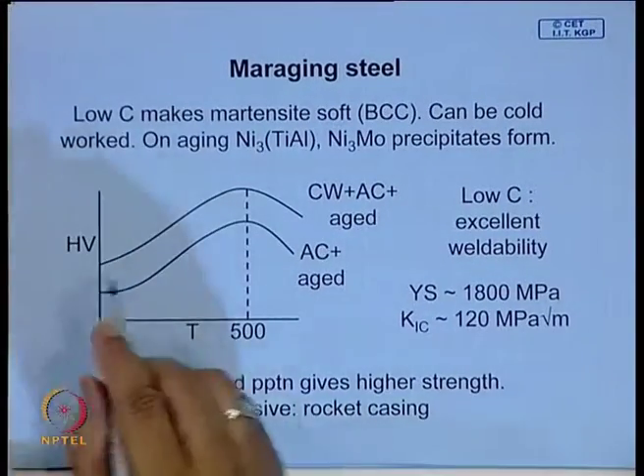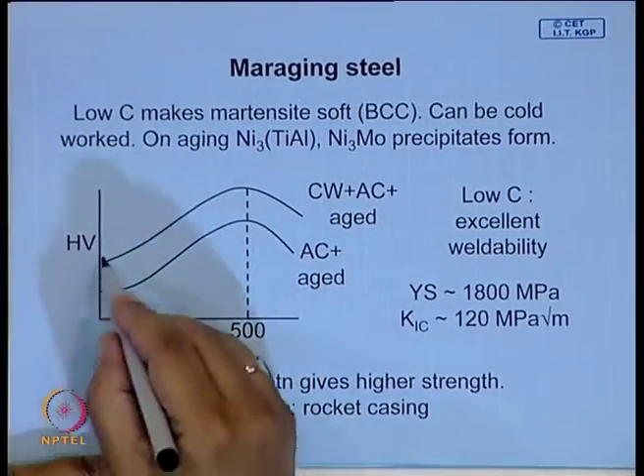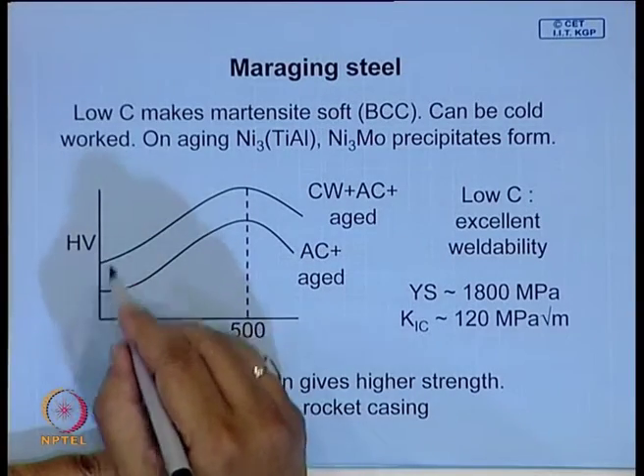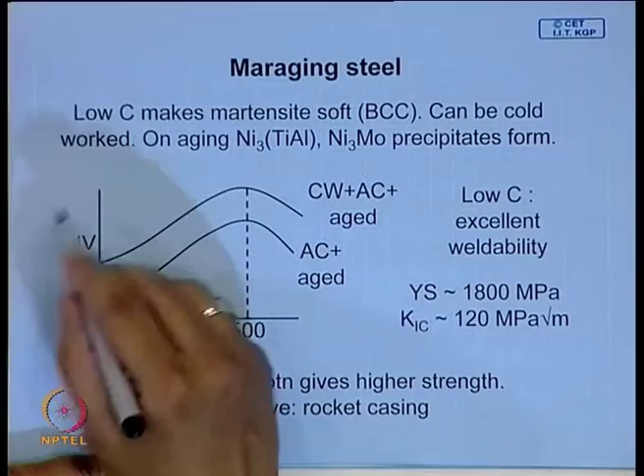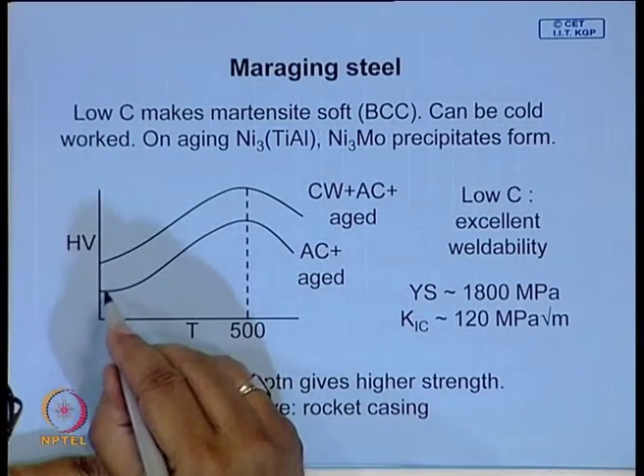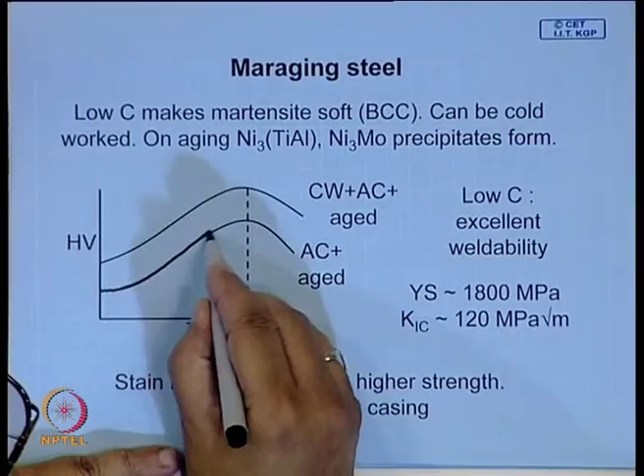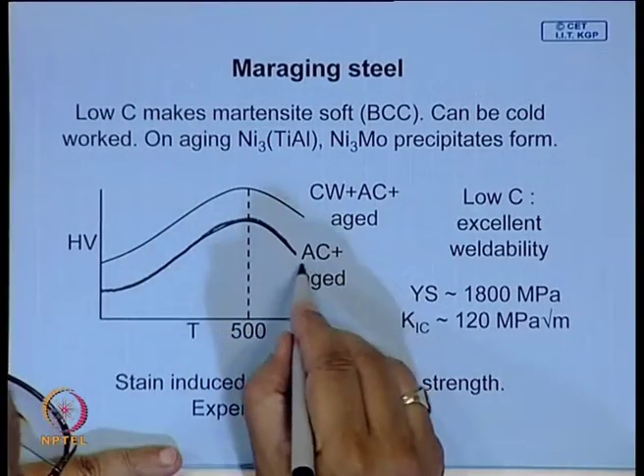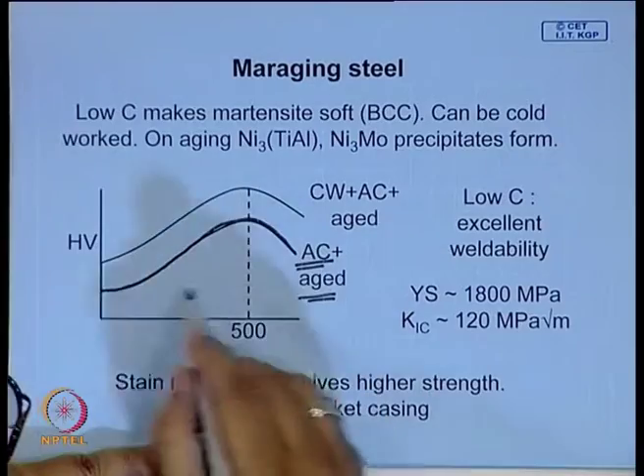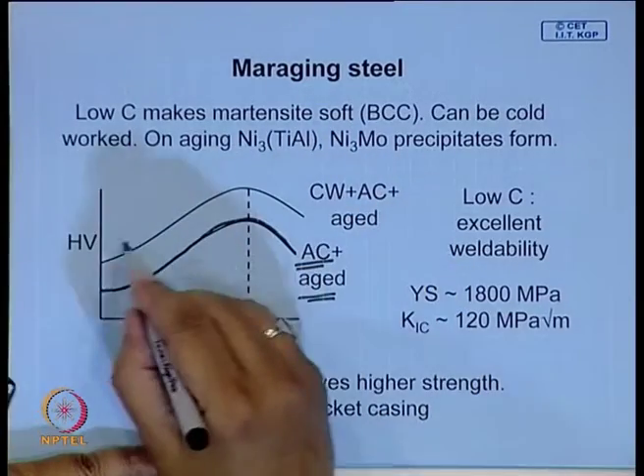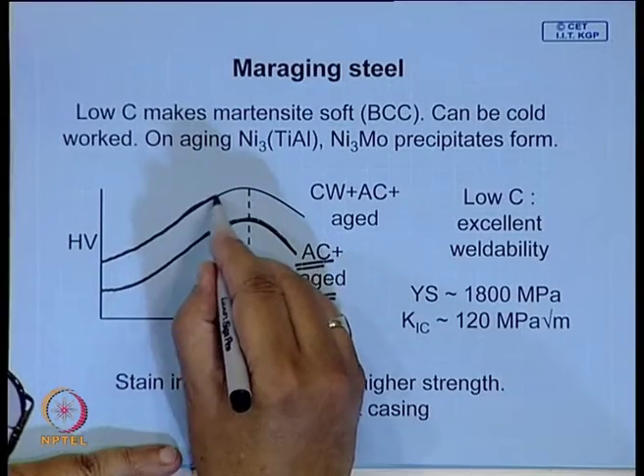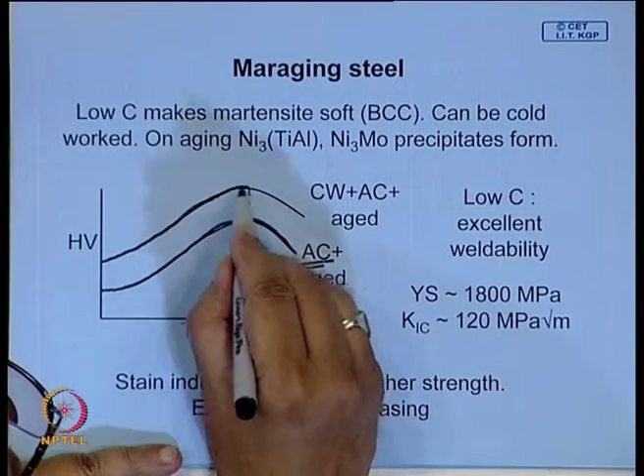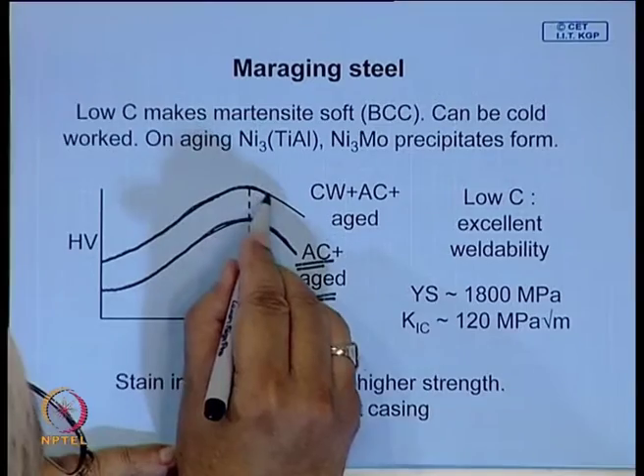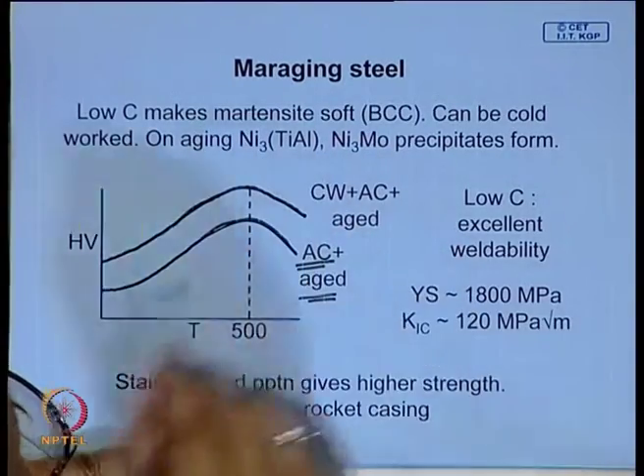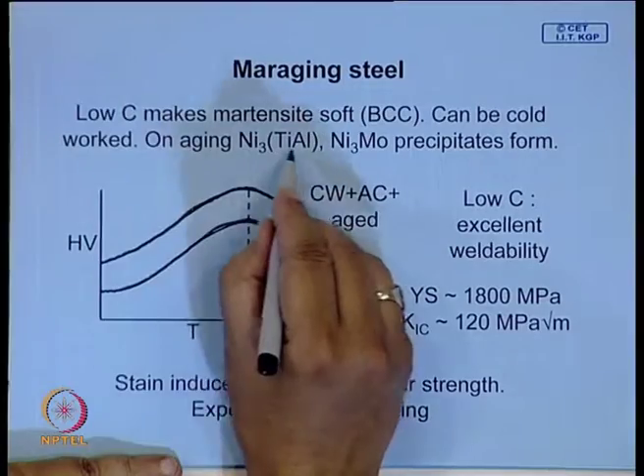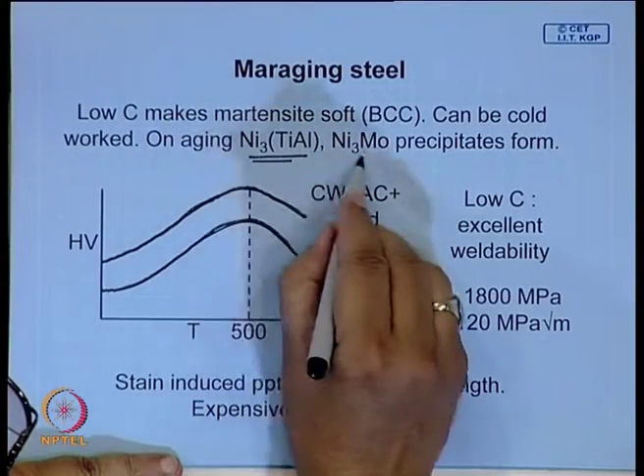And when you give this hardening treatment, aging treatment, the hardness goes up. If you do not give any cold work, then possibly the hardness increases like this. So, air cooled plus aged. Whereas, if you cold work and then age, then in the cold worked martensite, when precipitates form, it gives much higher level of strength, and on aging these are the precipitates that form.